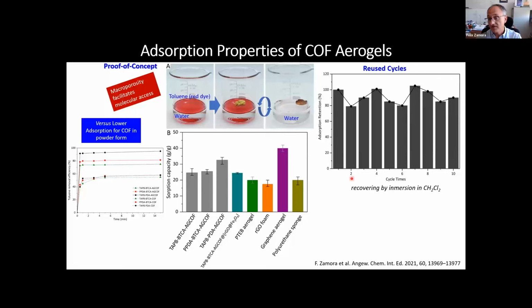So we were eventually able to recover the monoliths by immersion in dichloromethane. And as you can see here, these are the three monoliths, and we have relatively nice sorption capacities. We were able to remove between 25 and 35 grams of toluene per gram of COF. And if you compare these results with those obtained with the three solids with the same structure, these are the solids, and these are the three monoliths, you can observe that we dramatically enhance the sorption capacity of the material, probably because the macroporosity facilitates the molecular access to the toluene, okay, in these aerogels.